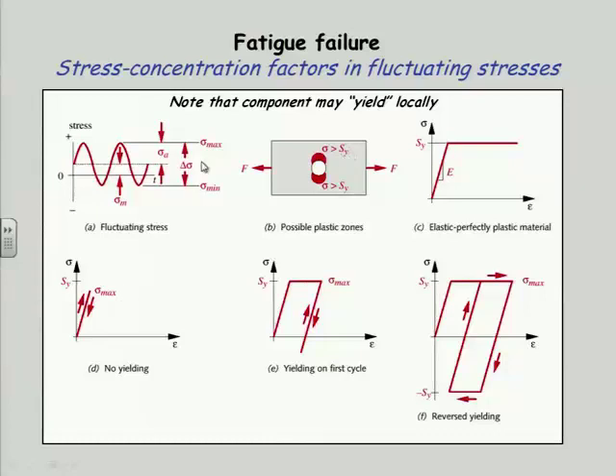So if we're going to simply calculate based on the largest load, the largest moment, the largest force, or whatever we might have, what's the stress under the maximum load? And does that exceed the yield point? If it doesn't, then we say, that's not a good situation because I'm not doing any kind of localized yielding to smooth things out and so forth. I'd better use the entire K sub F factor on the mean component as well. That's the conservative approach. On the other hand, if I do yield, then I could afford to knock down the K sub F a little bit to account for the fact that there's some correction going on in the material. And if I'm actually yielding both ends here, I could then probably just forget it and call it 0.